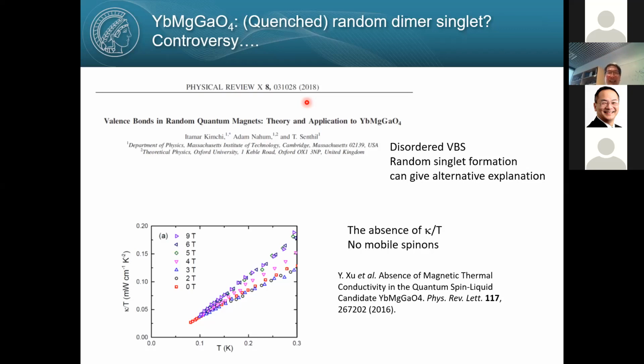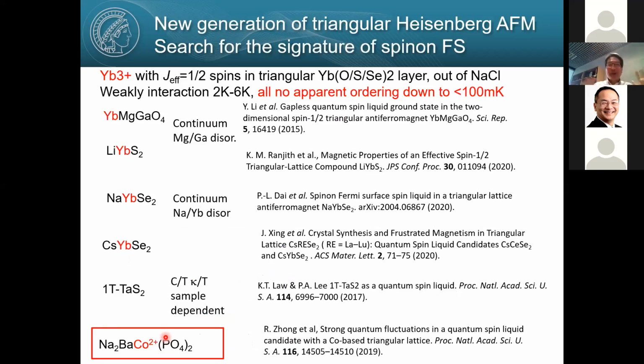And then theorists started saying that if we have randomly quenched singlets over space, not dynamically, quantum-mechanically fluctuating, but statically quenched, a singlet cluster can account for many of the experimental observations. Because of the random distribution, you have continuum excitation. And to support this, other people measured kappa over T, and they see kappa over T go to almost zero, no finite kappa over T. That means no itinerant spinon Fermi surface there. So in that sense, the situation is quite chaotic, unfortunately.